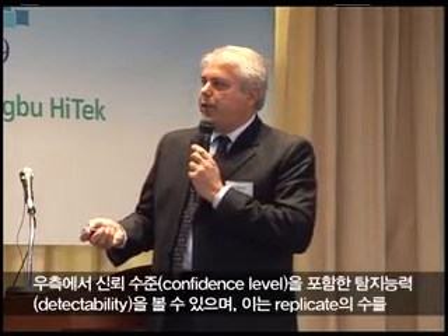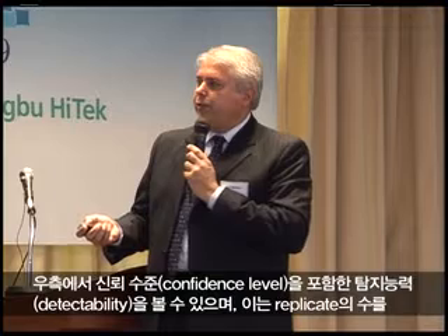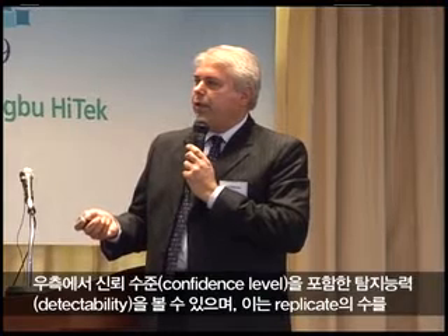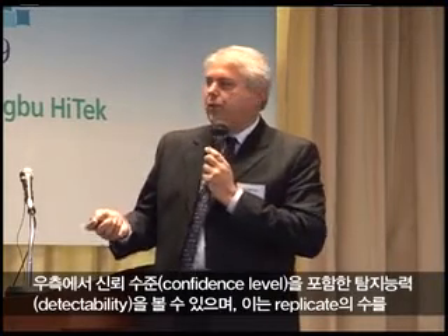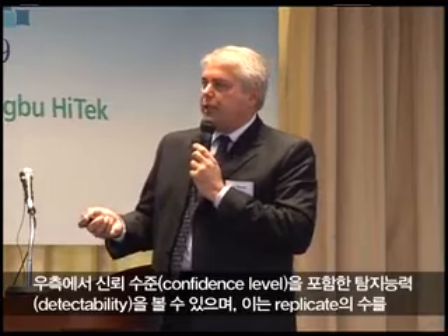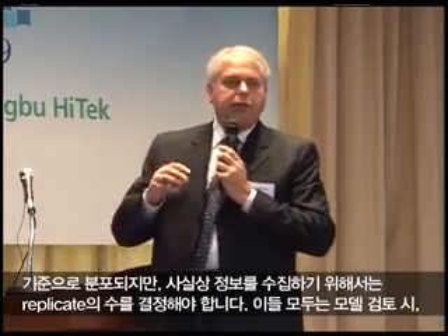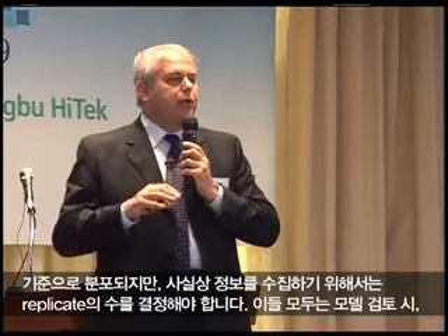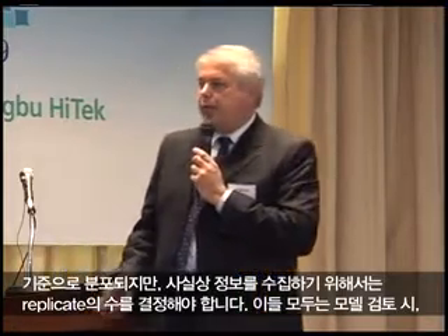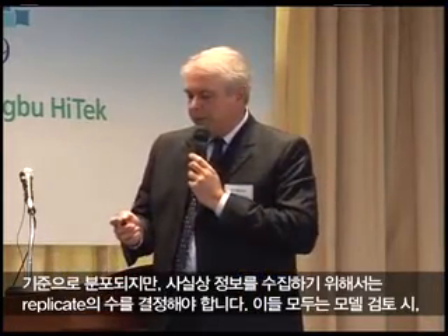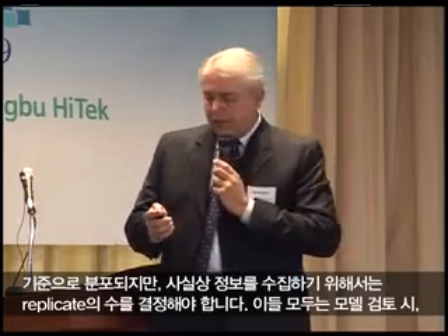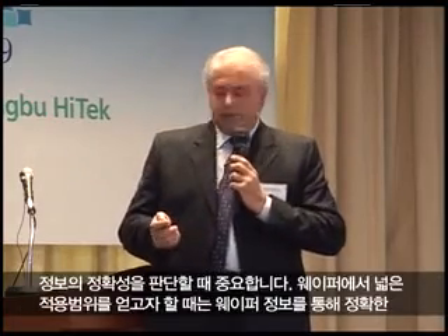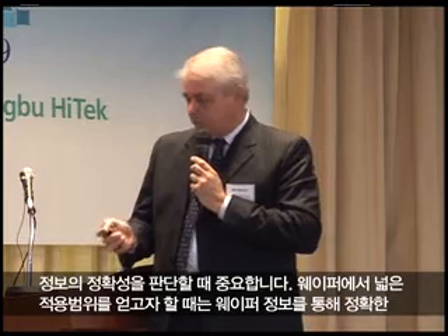And you can see that the detectability with the confidence level on the right side kind of saturates out with the number of replicates, but you actually do need replicates, and you can determine the number of replicates that are necessary to gather the information. And these are all important to determine accurately the information that will go into our models.